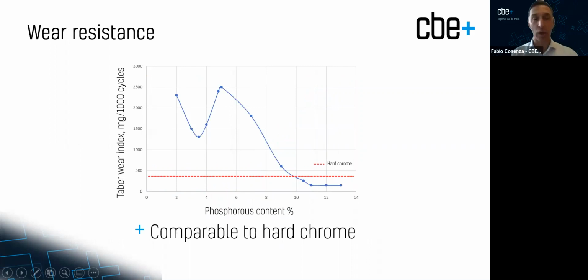Finally, we can increase the wear resistance of metal parts. Again, this is a function of the content of phosphorus in the plating bath. And once again, we seem to hit a sweet spot at 10% content of phosphorus, where ENP will basically perform the same way as hard chrome. Further increases in the phosphorus content can actually push the performance a little bit further than that of our competitor surface treatment.